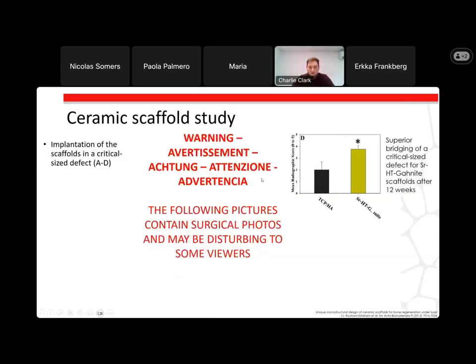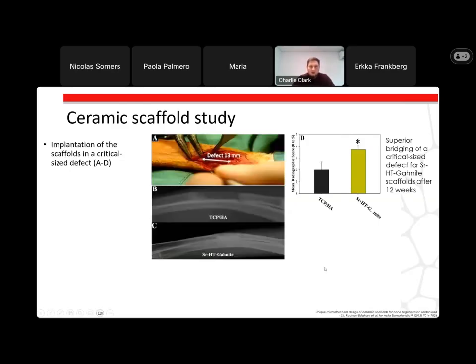Another warning, there are some more surgical photos after this. Look away now. So there was a study that was conducted with some ceramic scaffolds in rabbits. The scaffolds were implanted inside a critical size defect, which was around 13 millimeters. And what we could see from this was a superior bridging of the critical size defect for the new material compared to TCP and HA after 12 weeks, which we can also see in the radiography here.